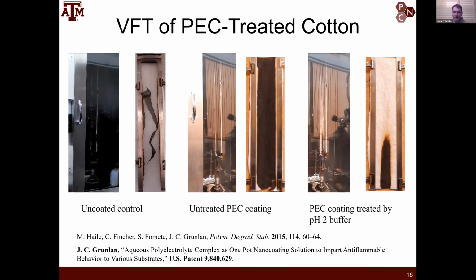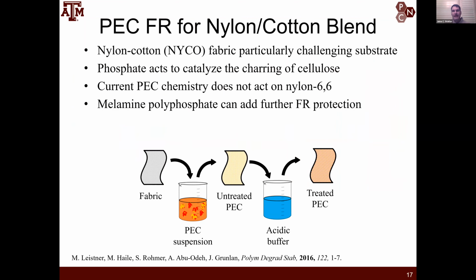You can see that some char forms, but then the rest of the fabric is unharmed because the intumescent action of that coating self-extinguishes the fire. Cotton is actually very easy to flame retard, so I always say you could spit on cotton and pretty much make it flame retardant, so that's not a big accomplishment.